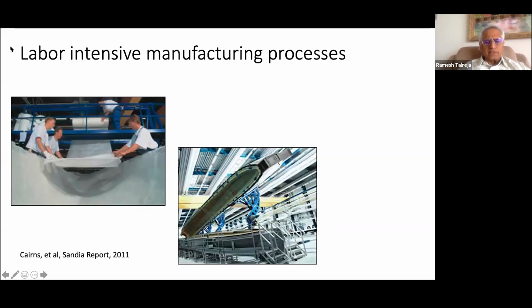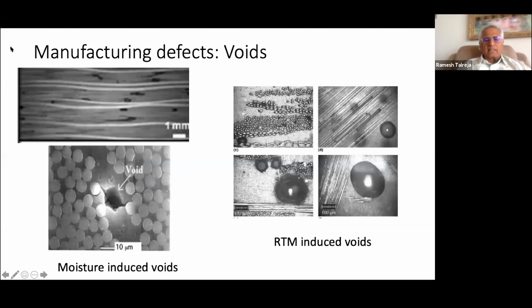So what you're looking at, this picture to the left is a hand layup of mats in the mold. On the right, you're looking at two parts of the mold that are being closed. And you can imagine that a lot of the labor-intensive input in this reduces the amount of control you can have in producing a quality product. Here are some laboratory examples of intentionally trying to see how defects will come about. So on the top left, you see a case where prepregs were removed too early from the bag in which they were enclosed. So this way, the moisture in the air settled on the surface and diffused itself inside.